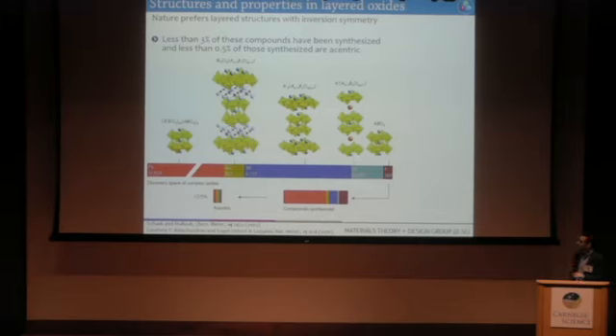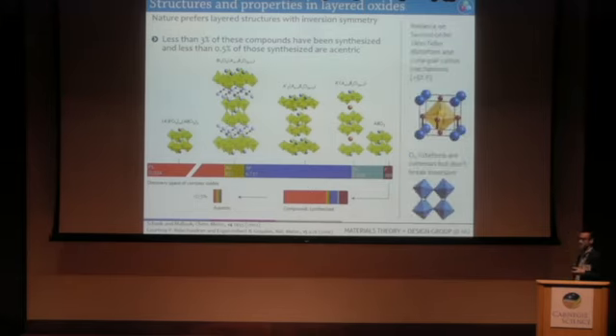And then if you compare this to what's been known, and if you think of what has been known lives in the ICSD, this is some small subset of that. Okay, and then if you focus on those compounds which have broken inversion symmetry, and not even just the ones that are polar, just the ones that break inversion symmetry, it's some small fraction of those synthesized compounds. So there is a dearth of materials which have broken inversion symmetry, at least in layered structures like this, in oxides like this. And we can rationalize this based on physics-based models of why this occurs.